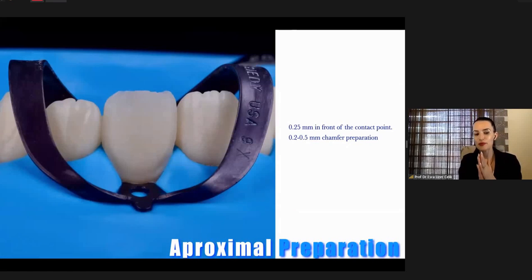Approximal preparation is also important. Generally, we don't want to open the contact points, and the preparation should end 0.25 millimeter in front of the contact points. A 0.2 to 0.5 millimeter chamfer preparation is preferred for approximal preparation.